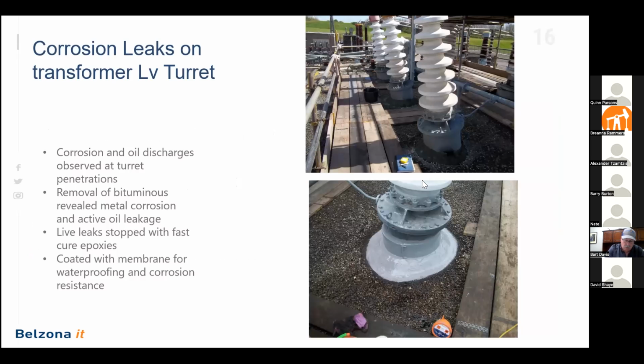And then finally, taking it to another step, at times there might be water damage, different damage, and there might even be some active leakage. So in this case, these were some transformer turrets, and they had this bituminous membrane here that was supposed to be the waterproofing. When they removed it, the metal was totally corroded, and there was actually some active oil leakage. So we were able to go in there, stop the live leakage with some of our leak repair materials. We've done a couple of webinars on those. And once we stopped the leak, we created our own seal with our membranes to stop this from happening again.